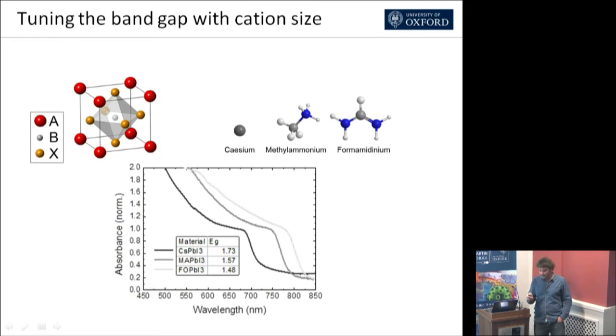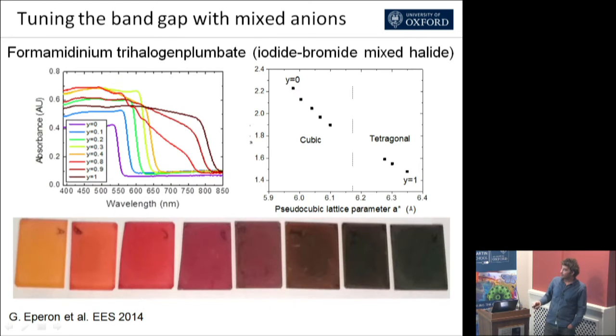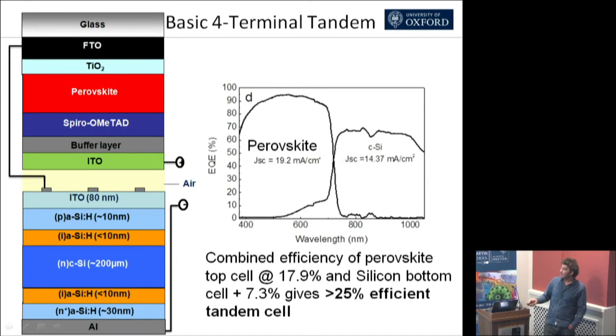I'm feeling like I might be getting a little bit technical here, so I'll very briefly scan over this. We can tune the band gap, because what's important is you absorb precisely half the light in the top cell, and the other half that you don't absorb in the top cell is absorbed in the bottom cell. You need to generate the same current from the 2 cells so that you have the best power matching. We can tune the band gap by changing the size of the cation here, or we can change the halide going from iodine to bromine. So it's very flexible in terms of tuning the material.